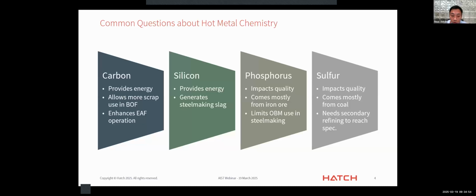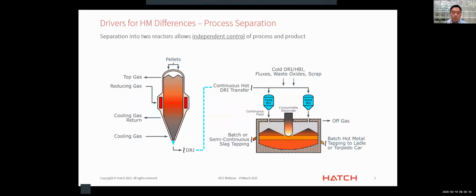Some BOF operators prefer to have some silicon to allow higher scrap usage. But again, because SiO2 is a slag component whereas CO2 is a gas, using silicon as an energy source in a hot metal unfortunately generates a lot more steelmaking slag. And that's actually one of the reasons driving why EAF efficiency comes down significantly with the presence of gangue material like silica.